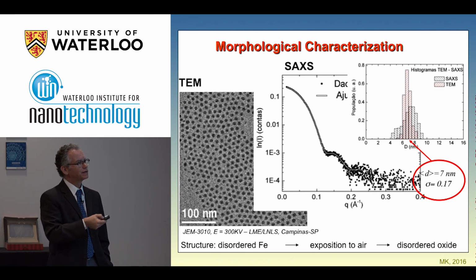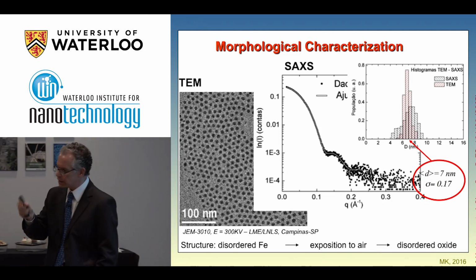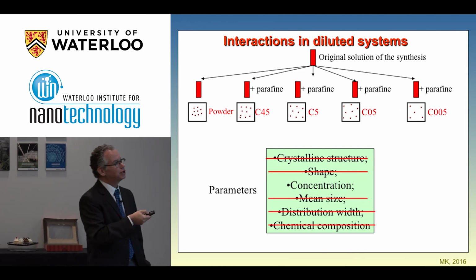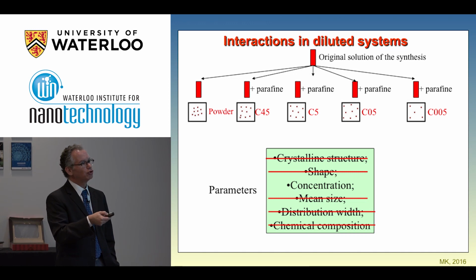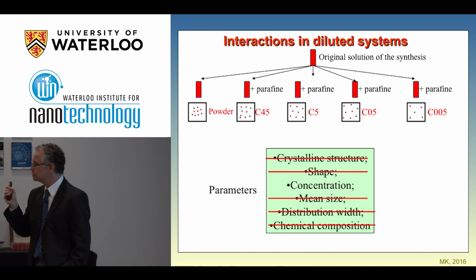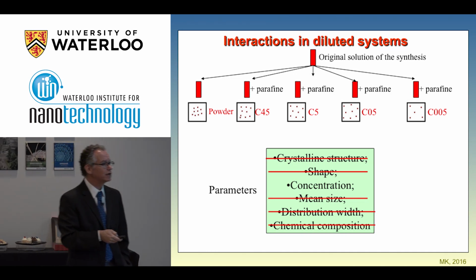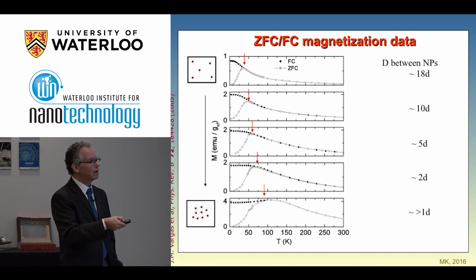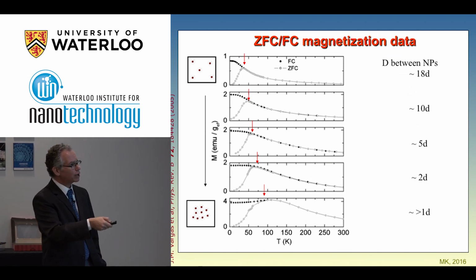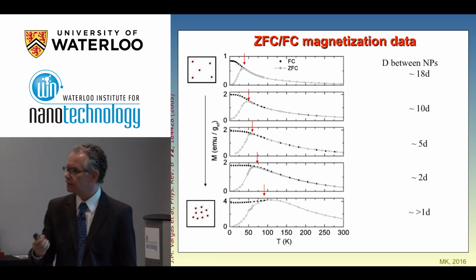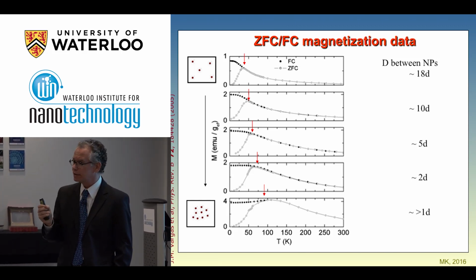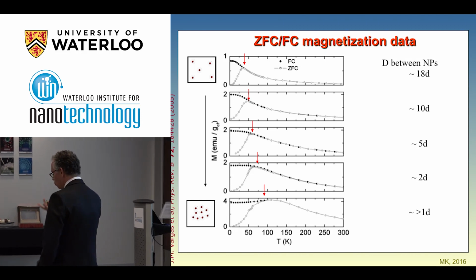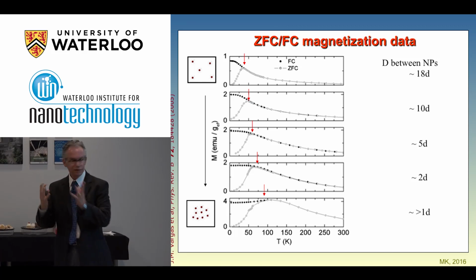So we have these very good samples now. We can study them in the synchrotron, as I showed before, by SAXS. We can have the microscopy here, and we can compare, and we can have a rather good picture of the structure. And then you can change the concentration by, for example, diluting them in paraffin. And so you have the very same sample, and just what you change is the concentration. So it's the same batch of samples, and you make different concentrations, and you can study, for example, the magnetization as a function of temperature, and you can see here clearly the blocking temperature going to higher temperatures. So it means that the dipolar interactions are playing a very strong role on the complex magnetization of the system as a whole.